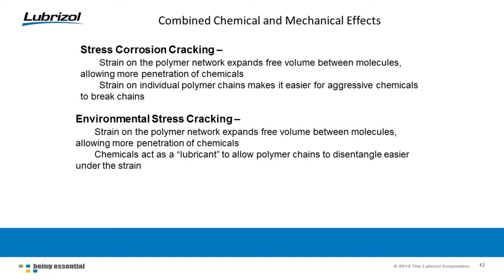With environmental stress cracking, the absorbed chemicals are solvents or plasticizers — there's no degradation of the polymer going on. Instead, those amorphous areas are having their entanglements undone. It's like putting olive oil on spaghetti — if you have spaghetti with no olive oil, it sticks together, but with a little oil the chains slide apart more easily. When the plastic absorbs something like an oil, a surfactant, or a solvent, the chains are easier to disentangle when strain is pulling on them.